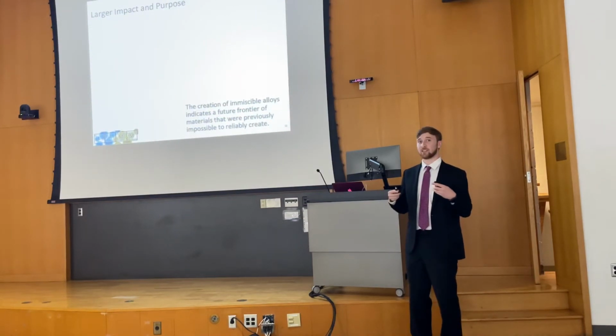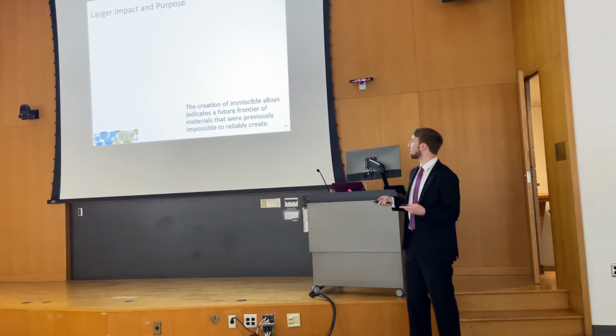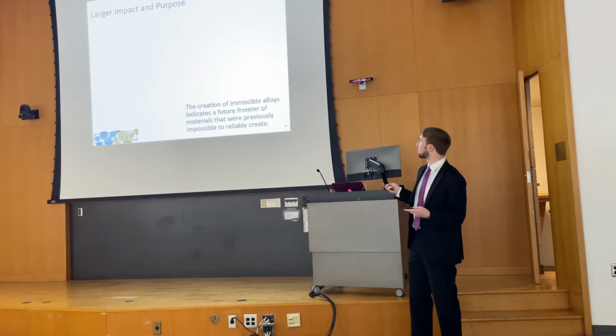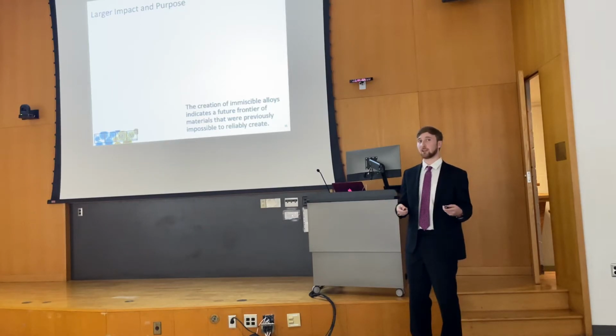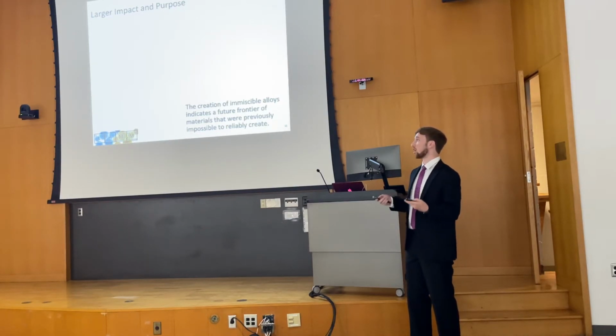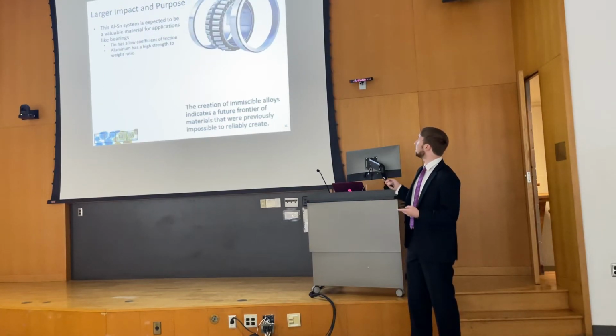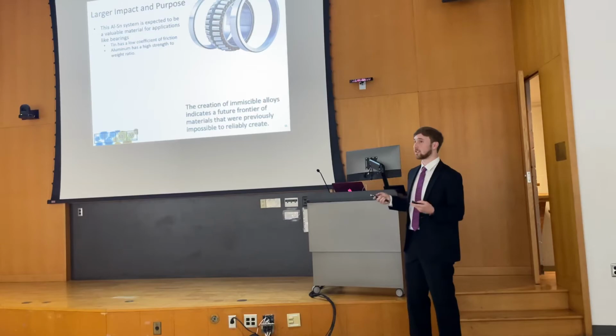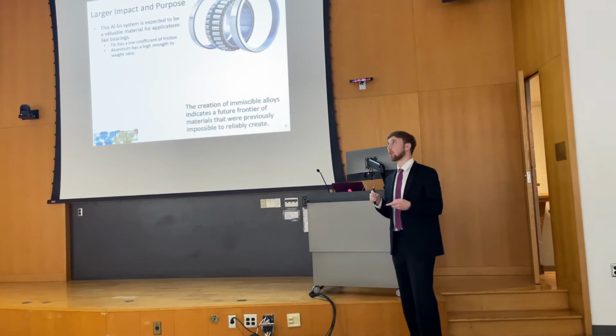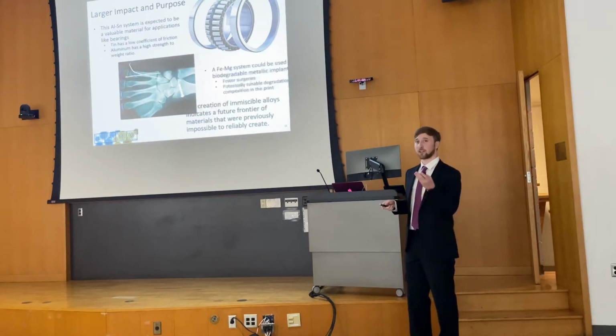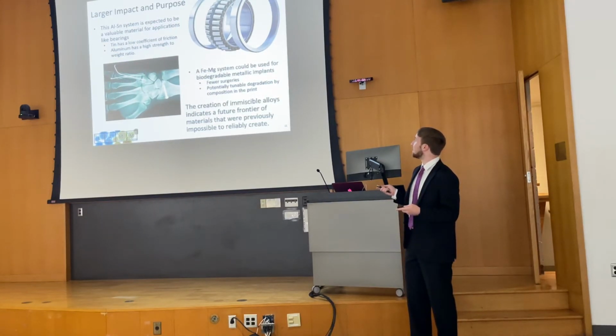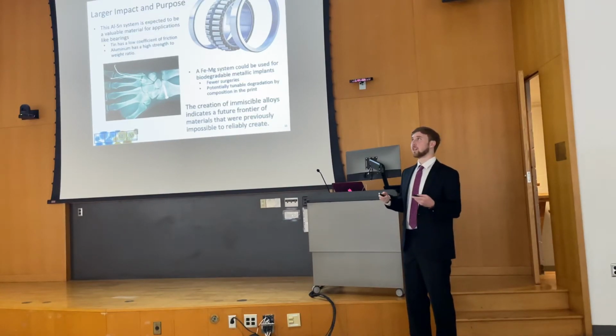So you may be asking, why does this matter? Why were you studying this? The larger purpose of studying immiscible alloys is it indicates a future frontier of advanced materials that you couldn't create by previous processes. And to put that more concretely, the aluminum and tin that I was working on is expected to be used for applications like bearings, because you could create an alloy with lower coefficient of friction than conventional aluminum and higher strength to weight ratio than conventional tin. Another example is one that my graduate mentor is working on, which is an iron magnesium system that could be used for intentionally biodegradable metallic implants, where there would be fewer surgeries because you wouldn't need to remove the implant after the fact.